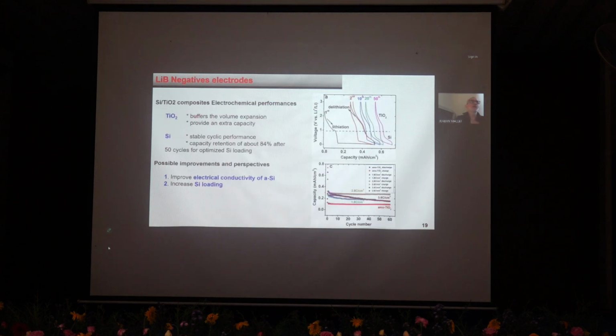So TiO2 creates a very good buffer for the volume expansion, providing also an extra capacity, because TiO2 is very relevant also for high-power lithium-ion batteries. And the silicon, thanks to this TiO2, performs very well with a very good cyclic performance. So here we have the capacity, and we see that the efficiency is very good. We are very close to 95% efficiency. And then the capacity retention is dropping depending on the quantity of silicon that we have.